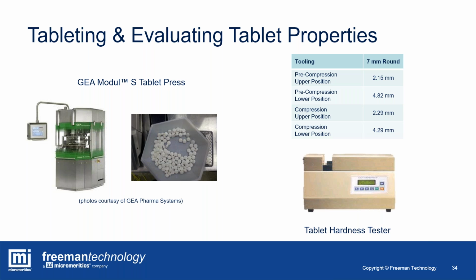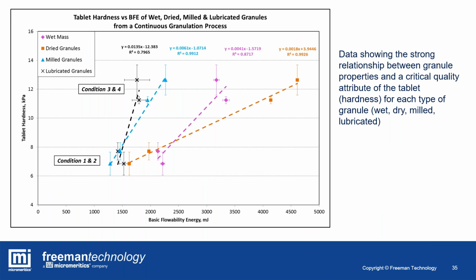And what we can see, again, is a graph with quite a lot of data, so I'll take some time here. It plots the relationship between the tablet hardness. So we simply made tablets in the hundreds from each of these 4 conditions. And it plots that hardness data against, on the x-axis, that basic flowability energy, that flow property data from each of the conditions. The wet mass is this magenta line, dried granules, and then the milled and the lubricated granules here. These are less differentiating down at this milled and lubricated end, but you can see here very strong and discerning differences between the granule attributes when they're wet, and particularly when they're dry, and tablet hardness.